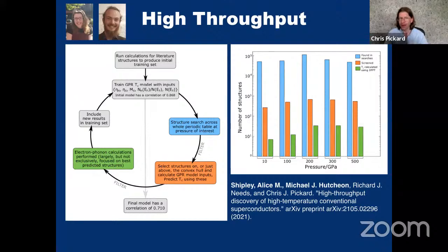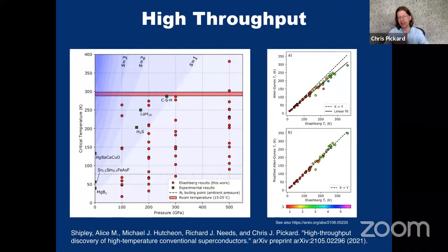But before Michael speeded things up by a factor of 10, you'd be rare to see a paper that was published with more than a couple of TC calculations in them. So that's our results. And then here's the outcome. I've plotted the pressure versus TC for our new structures. We found many potential hydride superconductors above 100 Kelvin.